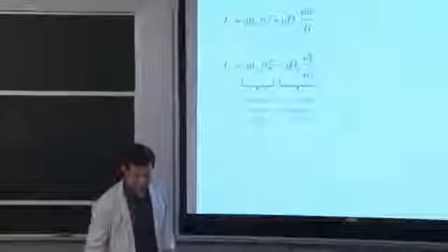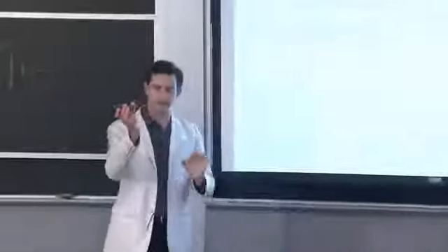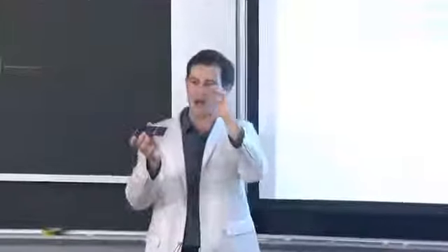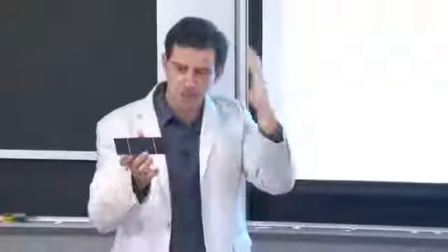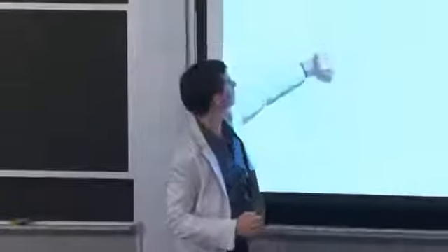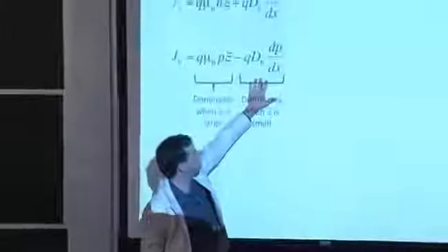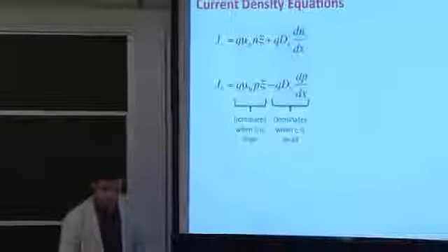So if we have a device like this right here, and if I told you that the built-in electric field was located, pushed up toward the top 1/100th of the device, so it was located very close to the surface, you might surmise that the drift current is going to have a large influence. If you're a single electron, you'll feel the influence of that electric field near the front surface of the device, and deep within the bulk, the diffusion current is going to be driving the carriers toward that junction.